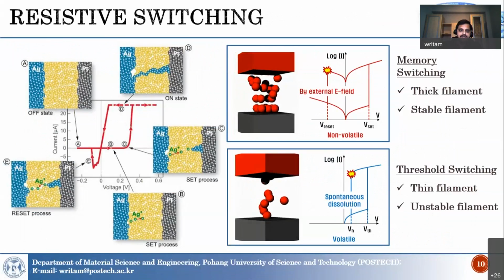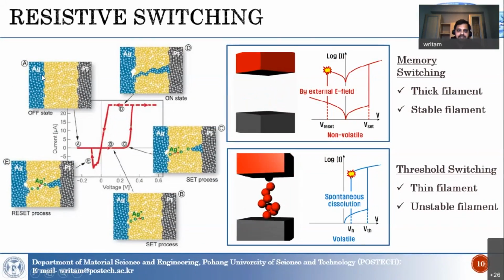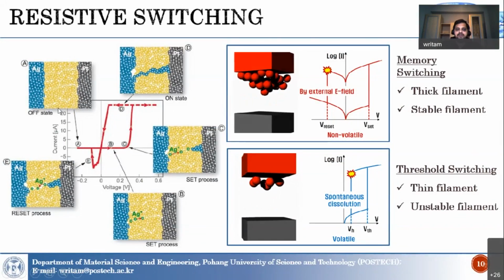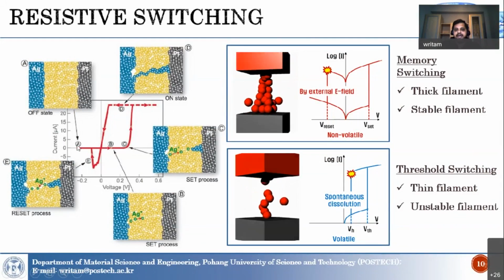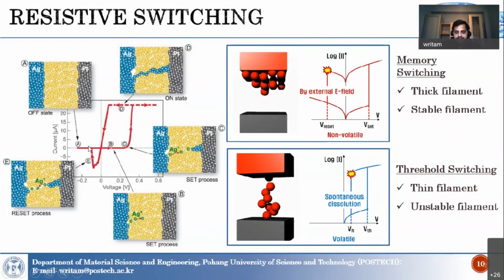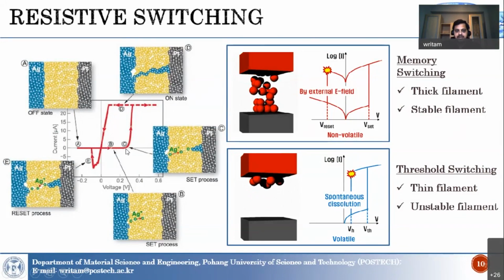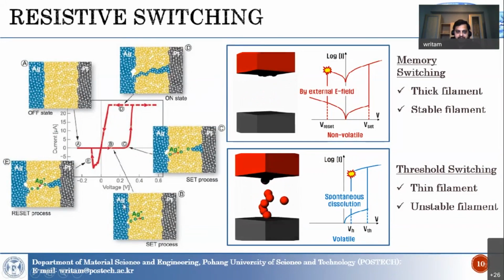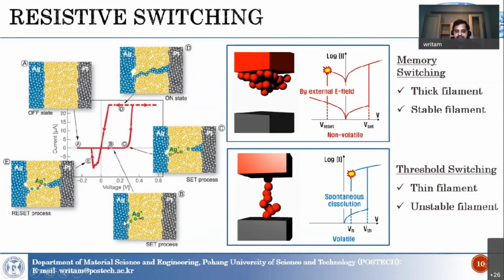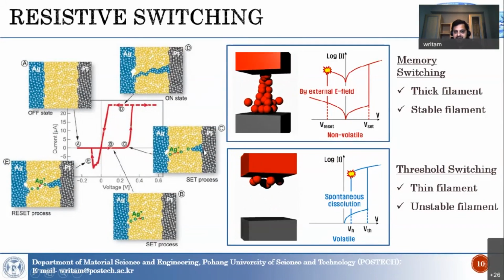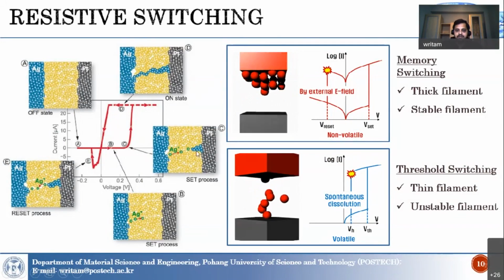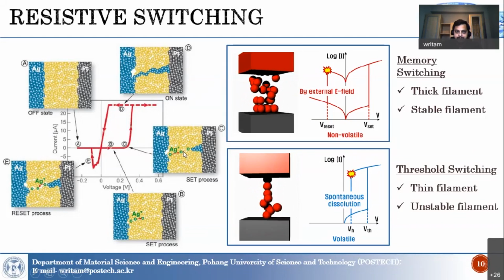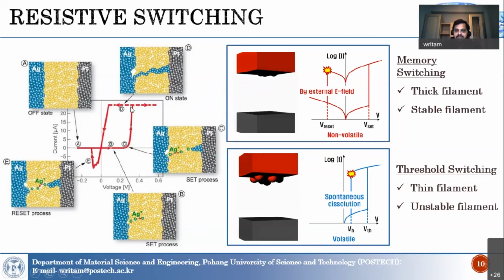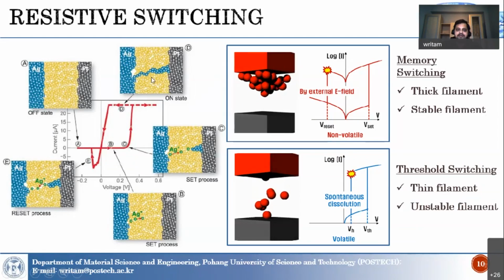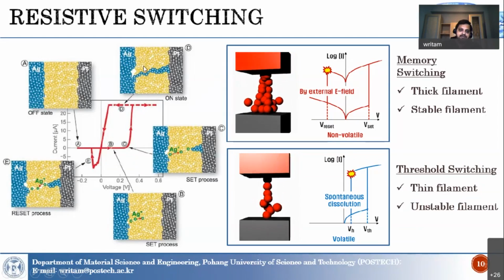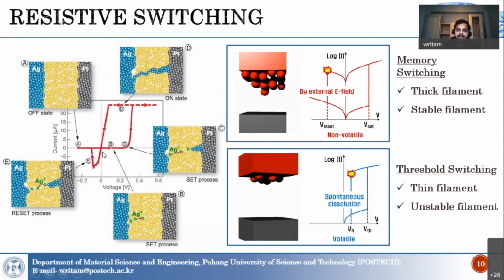Let us say you have silver, and this is Pt, and then some kind of oxide layer. Initially you are in a very high resistance state, and then with a biasing condition, positive bias here, the silver starts to migrate and nucleate somewhere on top of the bottom electrode side, and starts to grow, finally forming the filament. So basically you have the low resistance state, and then after a certain voltage, if you apply the negative side, you will break this channel and come back to the high resistance state again.